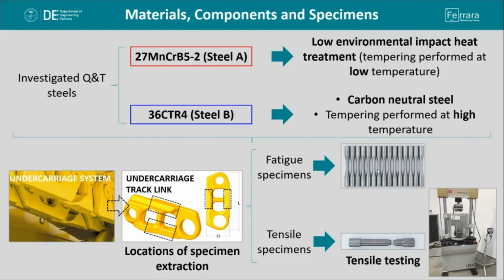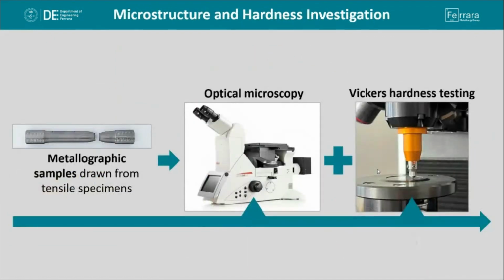And the company we worked with directly gave us the tensile and fatigue specimens we used to perform tensile and fatigue testing. Subsequently, the very first phase of the experimental procedure consisted in tensile testing performed on tensile specimens. In addition, metallographic samples drawn from broken tensile specimens were used to perform microstructure analysis and also Vickers hardness testing.